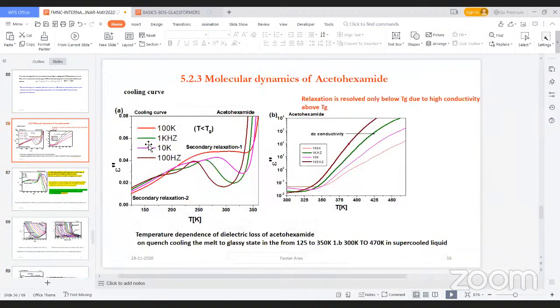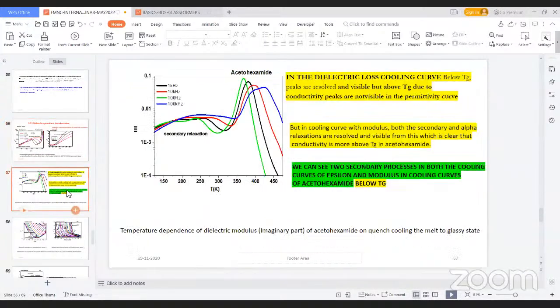And yeah, you can see here, this is the BDS curve of the acetohexamide during cooling. The dielectric constant and the temperature are plotted. For the 4 frequencies, you can see here at low temperatures, there is a curve corresponding to the secondary relaxation. In the same experiment, at high temperatures, you are getting some high values of dielectric constant, which corresponds to DC conductivity. But actually, there is a primary process, which, due to the high conductivity, is not observed, it is masked.